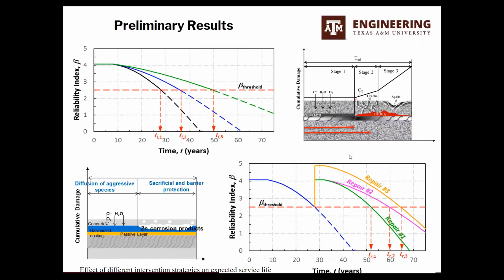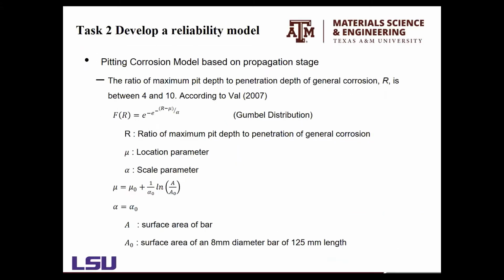And you see that this can be a repair based on the concrete, or a repair or an action based on the rebar. This is one of the things that I want to point out, and I'm going to do it fast, but nevertheless it's very important that the model that we are also doing in this project is a localized model. It's not only the general approach that I've seen most of the literature use. The general model is corrosion rate, but we now can prove that the localized attack is more threatening, which means that you have, let's say, 20 MPY in general, but there are points that have 30 MPY. So that's why we built this model, and we are validating this model as we speak, all right?